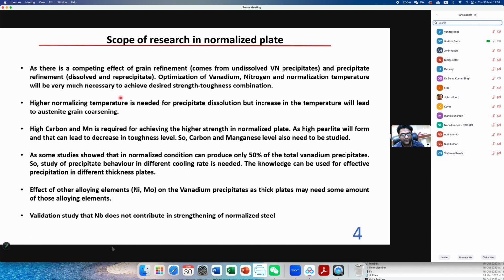So the scope of research in this normalized plate is that there is a competing effect of grain refinement and precipitate refinement, because the precipitates will dissolve and then re-precipitate. So we need to optimize the vanadium, nitrogen and normalizing temperature, so that we can get a strength and toughness combination. Higher normalizing temperature is needed for dissolution, but at the same time austenite grain will coarsen. High carbon and manganese is required for achieving the highest strength. So this was the scope of research.